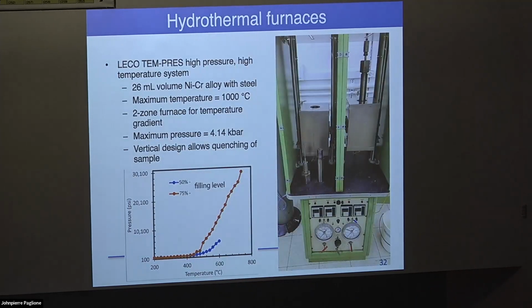But this is an example of a furnace using Tuttle type autoclaves. So you can see our version. This is the top here. This is the bottom here. This furnace, as you can see, is very old. But basically, it's a two-zone furnace for the hydrothermal autoclave to sit in, and we can control the temperature in the two different regions of this furnace to do a seeded crystal growth if you needed to.